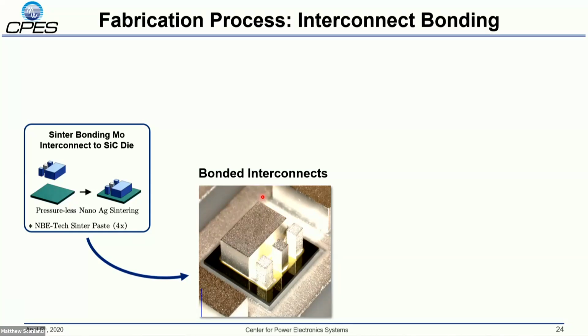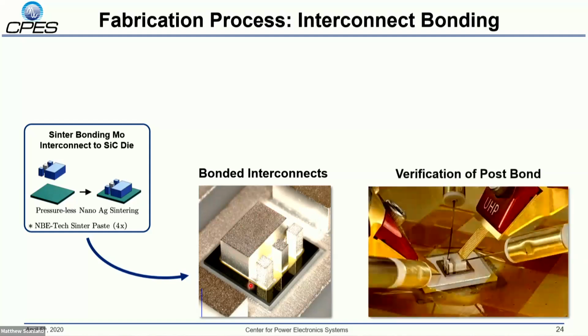But this is what the die looks like with the molybdenum post centered to the top. Most of this goes together with silver sintering. So the posts are silver sintered to the top of the die. And then the dies are individually characterized after each step of the fabrication. This is a byproduct of having to assemble this by hand.